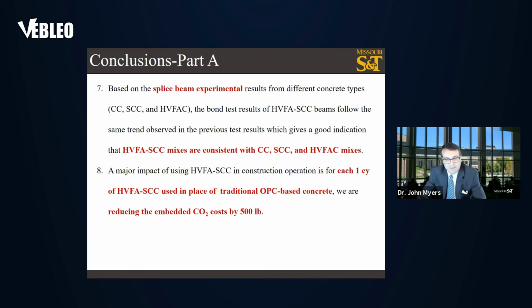And most importantly, from the perspective of sustainability and CO2 emissions, each 1 cubic yard of high volume fly ash SCC used in the place of a traditional ordinary Portland cement based concrete would be reducing the embedded CO2 costs by 500 pounds.